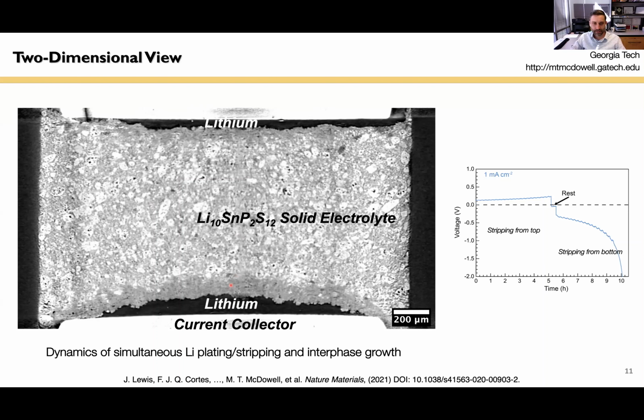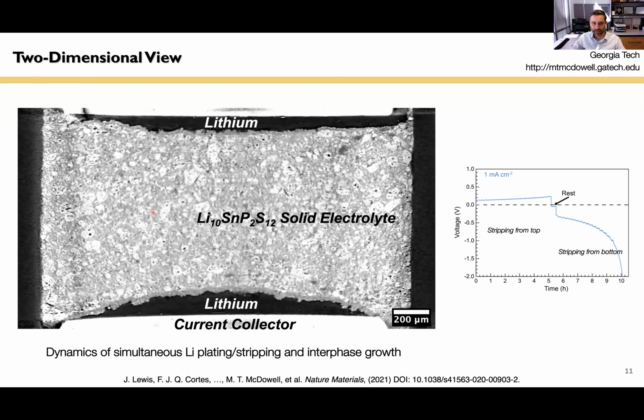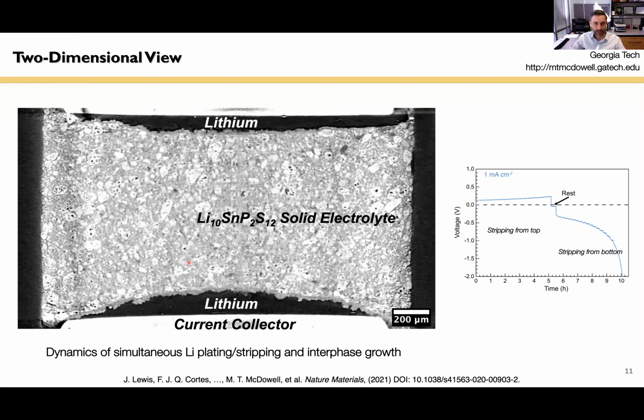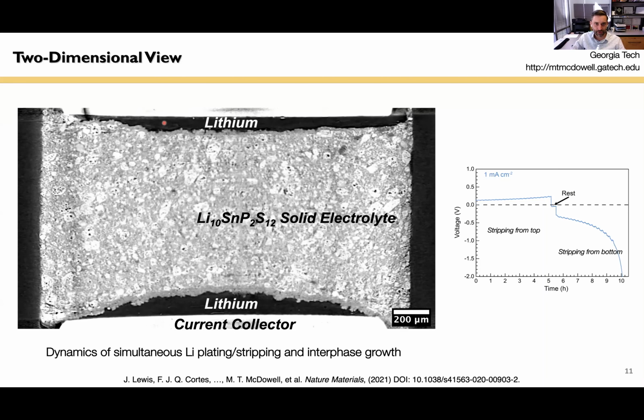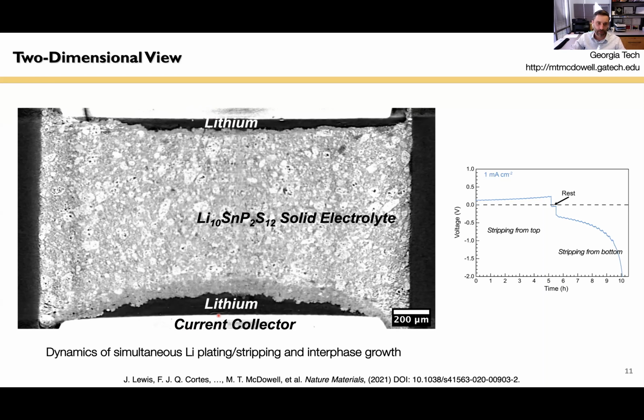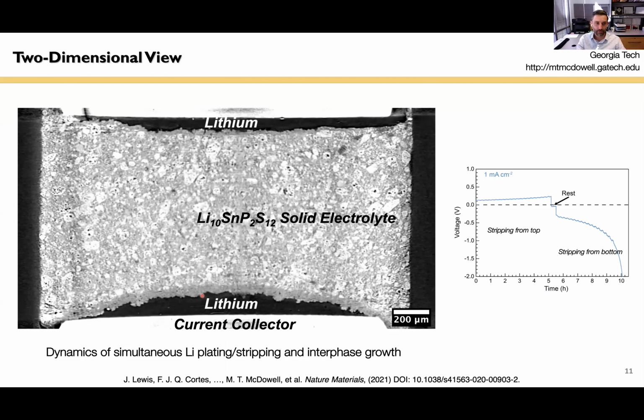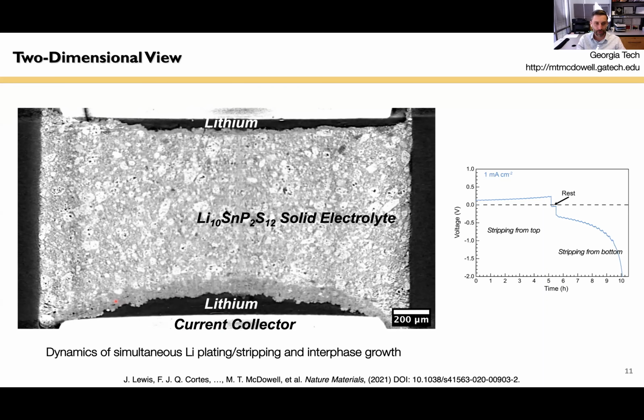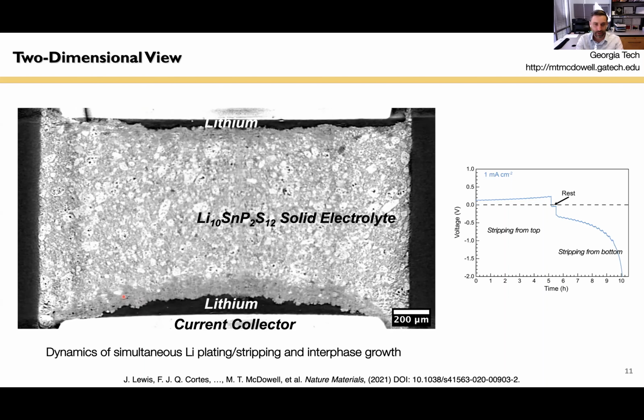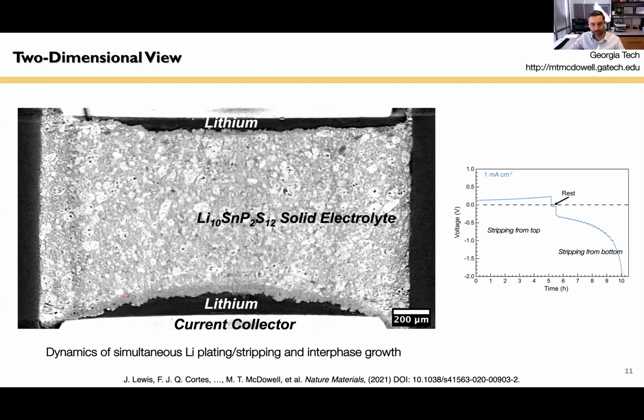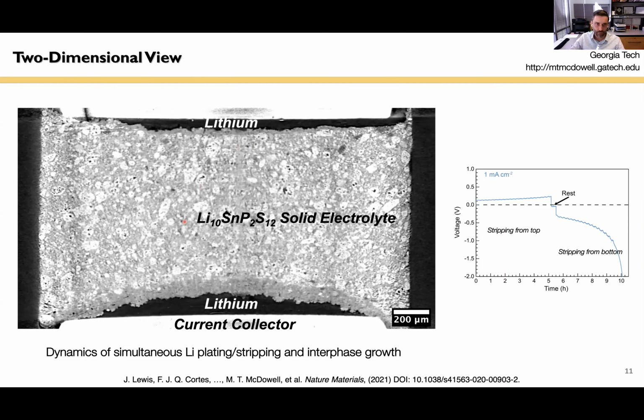And what we're seeing here is basically the reaction processes in this cell over about the 10-hour experiment. And what you see is the lithium metal electrode shrinking at the top and then at the bottom as we're stripping lithium. You also see this intermediate contrast region growing at the bottom and then the top. This is the interphase. So I mentioned this earlier. What we're doing here is we're directly electrochemically growing the interphase, which is the reaction product of the solid electrolyte with lithium. We're doing this instead of depositing lithium metal in this system. We're growing interphase. So here you can see it growing at the bottom. Here you can see it growing at the top when we switch the current. So upon reduction, we grow interphase in this system.